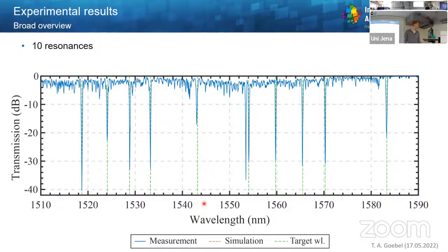Additionally, what you can see, we have this kind of underground around our resonances. Some part of this is due to coupling into cladding modes. Because we make a very localized structure in our fiber core, the light is partially coupled from the fiber core into the cladding of the fiber, and so it's lost in transmission. But not all of these peaks correlate to cladding mode coupling.